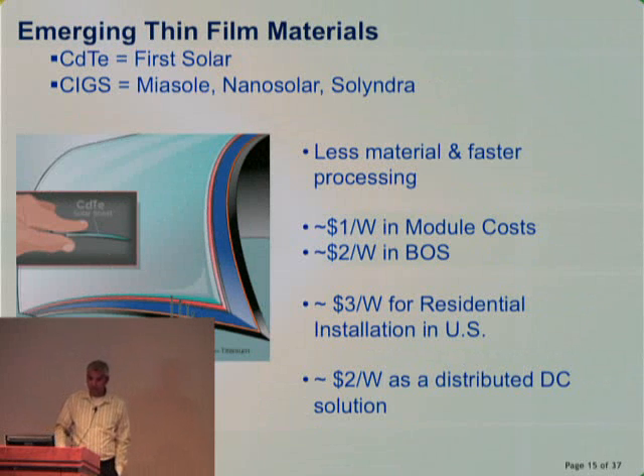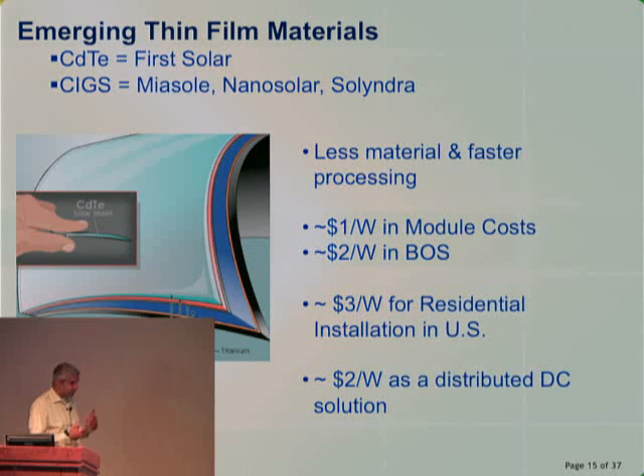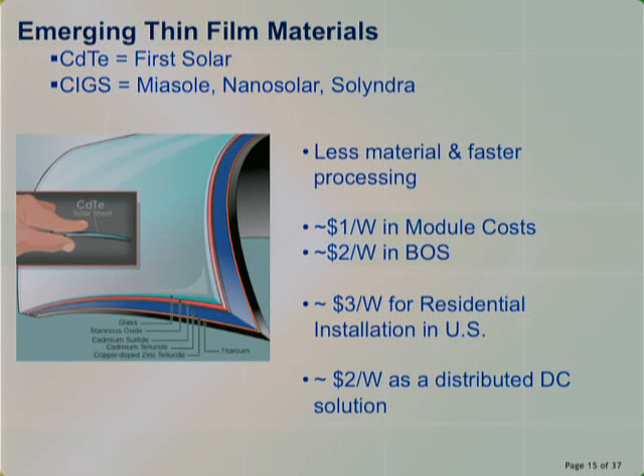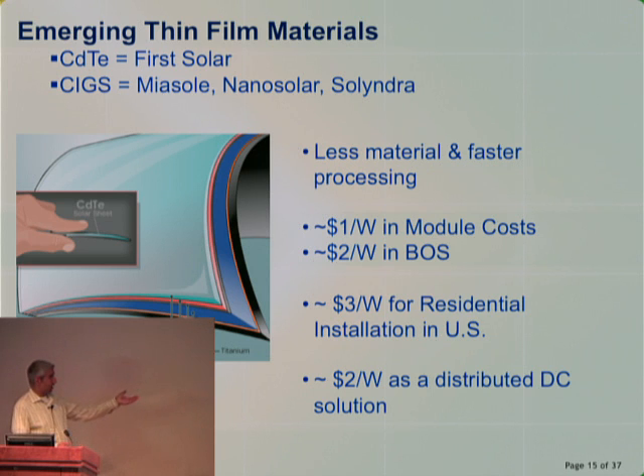So that's silicon. But then in come thin films, and thin films are a really exciting new development in the solar industry, because basically two technologies, CdTe and CIGS, have found a way to use less material and process it faster. They, in fact, have come down to about $1 a watt in module cost, and that's CdTe, that's First Solar specifically. I just talked to a fellow at First Solar yesterday, and he says that they actually are down to about $2 a watt in balance of systems. So now we're down to $3 a watt, a tremendous leap from that $8 a watt that we were reporting just last year. So we've solved it, right?